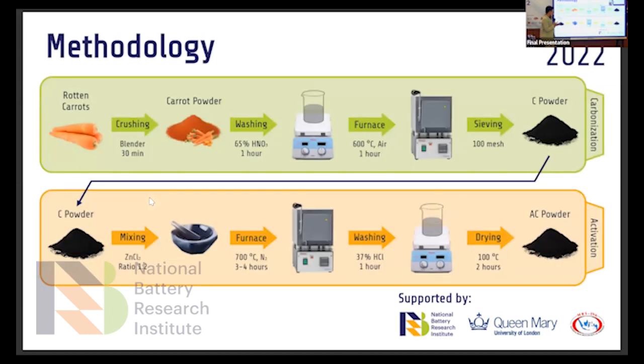Next. Our main material is clean dry rotten carrots. The first step is carbonization, with nitric acid used to remove impurities. After that, we carbonize the carrots at 600 degrees, and then we mash and sieve the carbon into carbon powder. The second step is activation by zinc chloride chemical activation and physical activation with 700 degrees furnacing or calcination in a nitrogen atmosphere. The result is then washed with hydrochloric acid and dried to get the AC powder.